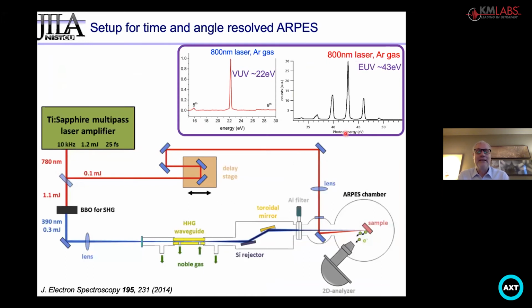You take your Ti-Sapphire laser, that's a KM Labs Rhea laser. You take part of the beam from the laser and use it as a pump pulse. You have a delay stage in there, so you can vary the pump probe delay. Then you use the majority of the light to drive the higher order harmonic generation process. You have some optics to eliminate the co-propagating laser light and to select a single harmonic.